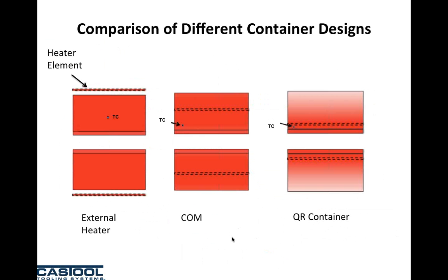One other benefit, if we go back a slide, is energy consumption. As you can see, having a hot container and a hot container housing costs a lot of money. If you allow the container housing to be 200, 250 degrees Fahrenheit, and your container to have both a longitudinal and diametrical gradient, we can reduce energy costs anywhere from 50 to about 70%, which is considerable when you look at it day after day, month after month.